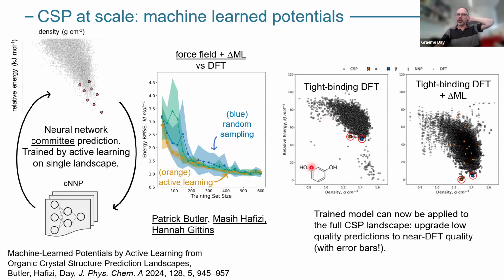Here we looked at this molecule resorcinol. And if you do crystal structure prediction for resorcinol with tight binding DFT, so it's a cut back version of density functional theory, it doesn't do very well. You get the known polymorphs of resorcinol, but they're ranked really poorly in energy. But you can use this kind of approach of taking a few structures out, training a machine learned model to correct tight binding DFT, and then apply that correction to the whole landscape. And then what it does is it brings those observed structures down to the bottom. Okay, so we can very quickly and efficiently improve qualities of CSP landscapes.